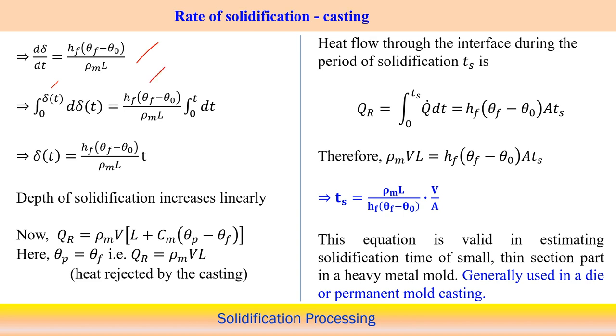Now we can find out delta t by performing the integration: delta t equals h f (theta f minus theta 0) by rho m l into t. So this is the variation of the solidification front at a particular time t. It depends on the film heat transfer coefficient h f, the difference theta f minus theta 0, where theta 0 is the initial temperature, and rho m l, the density of the cast metal and the latent heat, and on the thickness of the solidification front at time t.